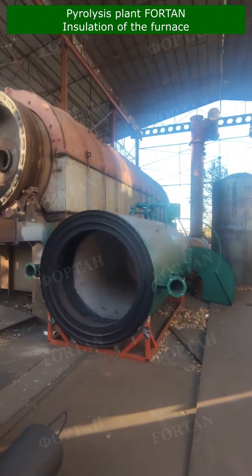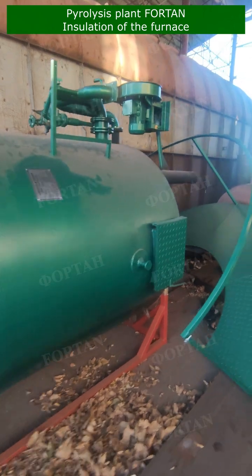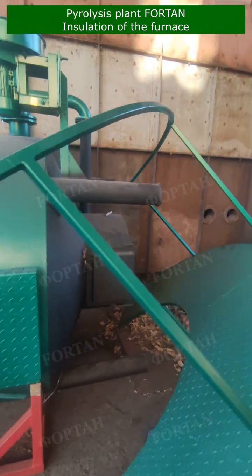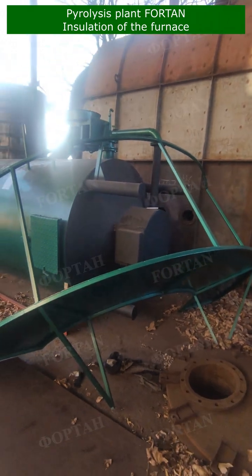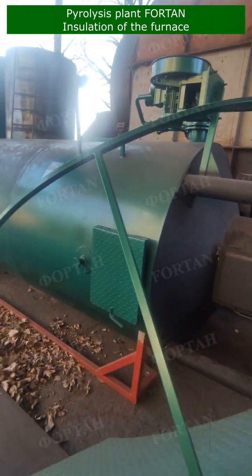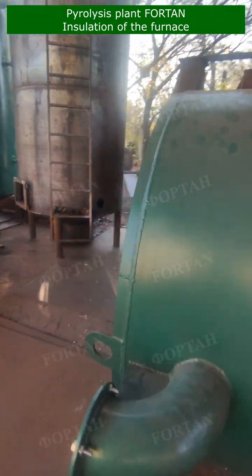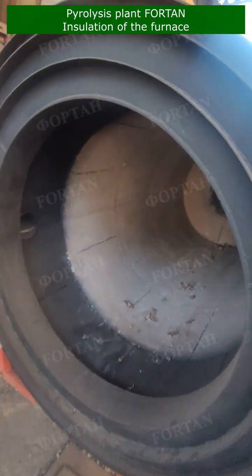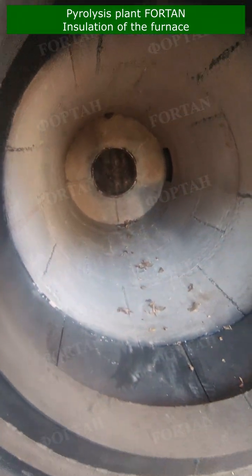Here the furnace lies horizontally. This is how it is transported. You can see that the concrete is supported by the furnace body. It does not require dismantling during transportation, unlike fire clay bricks. The total thickness of the lining is 15 centimeters, the service life is 10 years.